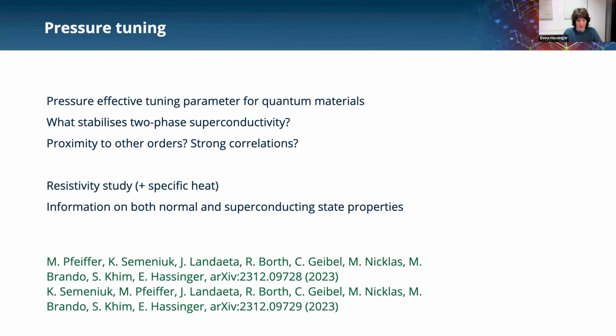Okay, so what we did now, and what I'm going to show you for the rest of the talk, is we carried out resistivity measurements under pressure, because pressure is a very effective tuning parameter in heavy fermion systems. And we try to find out what stabilizes the two-phase superconductivity and what's the relation to the proximity to other orders, and how correlations influence the two phases. And we have put two papers on the arXiv that cover the normal state and the superconducting state under pressure.